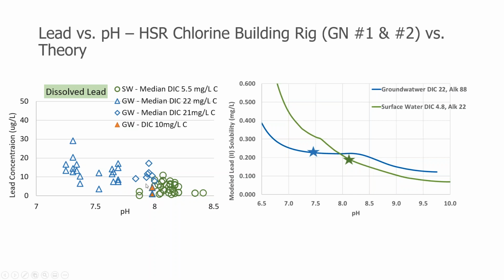There were a few days when the wells were operating and a low DIC groundwater came into the plant, DIC down to 10, and that behaved almost more like a surface water with that low DIC, and we do see significant lead reduction at the higher pH. But for the higher DIC waters, it's some improvement, but not much. So it really did perform quite similar to how it would be predicted by the solubility. Again, this is just in terms of trends. The numbers in the solubility models are often much higher predicted. They assume equilibrium with pure lead surfaces and infinite contact time and all that kind of thing. So we get much higher numbers, but the trends are what we look for on the solubility models.